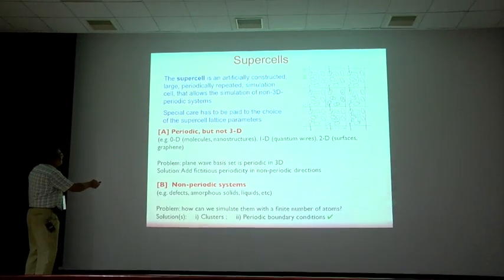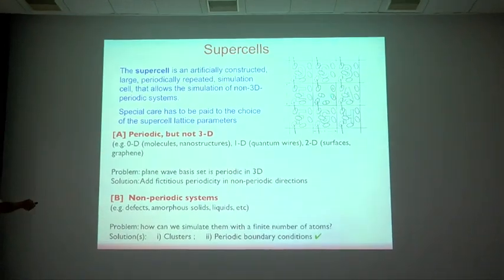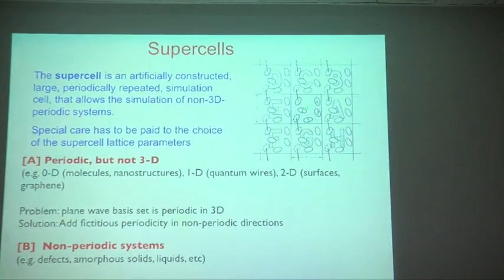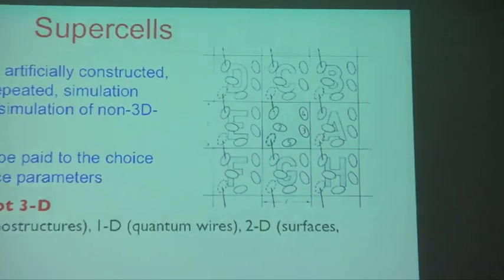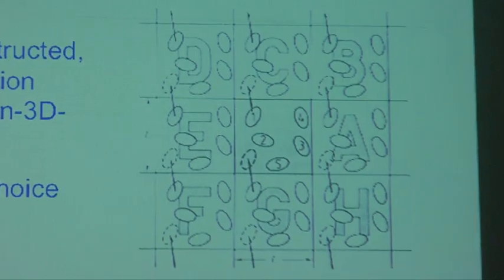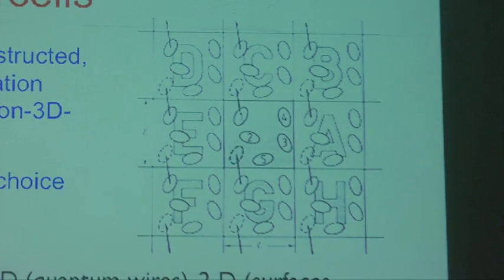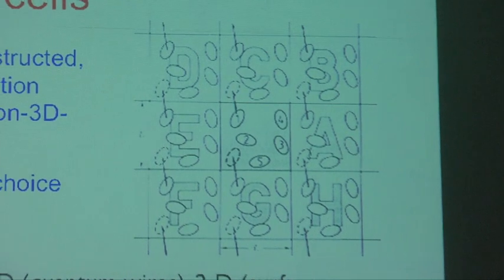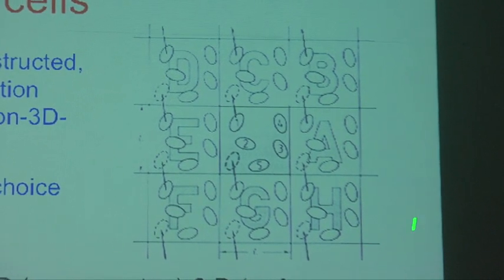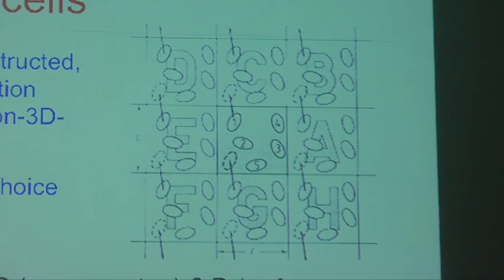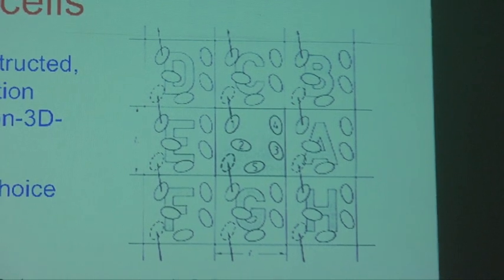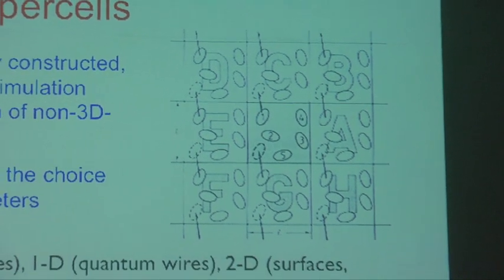And so your supercell is now a 3 by 3, let us say, only with the central one replaced, one gallium with manganese, and then repeat. Fine, you have done it. Now you want to find out what is the difference in energy. So you have to subtract whatever result you get from the DFT calculation on this supercell from another calculation which is without defect.